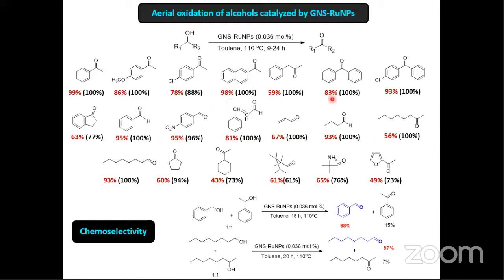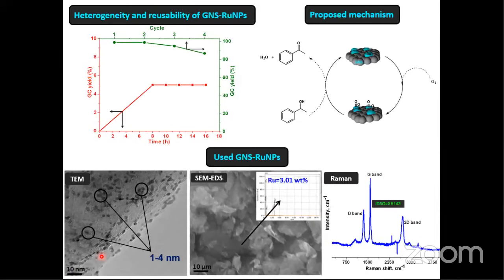And we have obtained different carbonyl compounds. Even we could oxidize the aliphatic alcohol to carbonyl compound. The oxidation of aliphatic substrates is very difficult, right? But this could catalyze very efficiently. There is even selectivity. This ruthenium-based nanosystem also catalyzes preferentially oxidation of primary alcohol compared to oxidation of secondary alcohol. That has been established in the aromatic system as well as in the aliphatic system, right? After the reaction, there is a slight increase in the particle size.